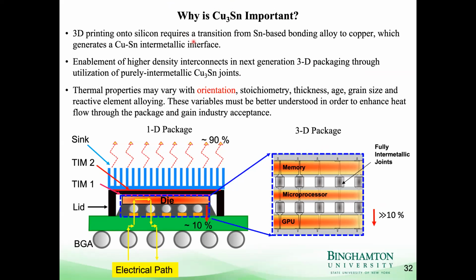So even though this material is quite important, there's never been any thermal anisotropy measurements of this material. And the only anisotropy transport measurements were of electrical properties of a liquid phase electroepitaxy, which showed a very high anisotropy of about 3. So we wanted to know, does that really apply for more conventionally made Cu3Sn joints as well?